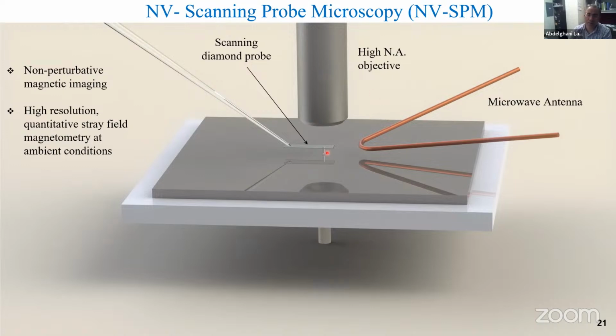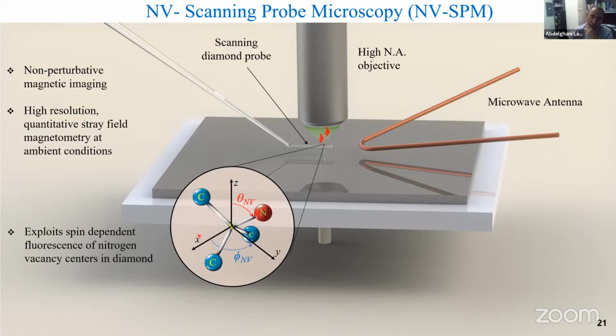In principle, you have a diamond probe with a single NV. We get these commercially. You have the laser here, focused through a high NA objective. Then you get some light emitted, and we collect that light using single photon detectors. If you look at the schematic here, it depends on the axis. The NV axis can be, in the case of 100 diamond, oriented at an angle of around 55 degrees.